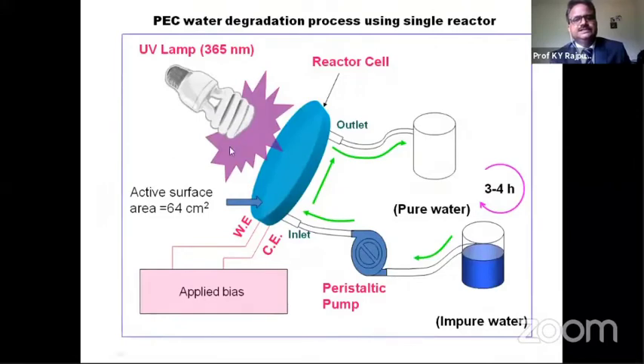So here, this is a PEC reactor, and there is an animation. The electrode is given a bias. It is illuminated with UV light, and polluted water enters, and at the outlet relatively pure water comes out. And if it is continuously circulated for 3 to 4 hours, then it is possible to get potable water out of impure water.